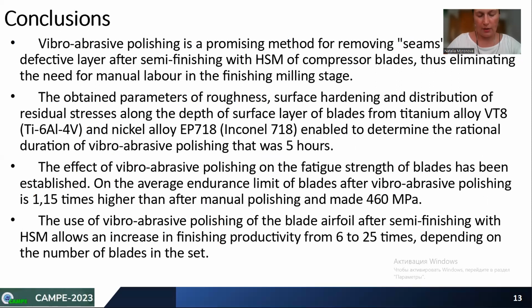The following conclusions can be made from this study. Vibro-abrasive polishing is a promising method for removing seams of the compressor blades, thus eliminating the need for manual labor at the finishing stage. The obtained parameters of roughness, surface hardening, and distribution of residual stress along the depth of the surface layer of blades from titanium alloy VT8 and nickel alloy Inconel 718 enabled us to determine the optimal duration of vibro-abrasive polishing, which was 5 hours.